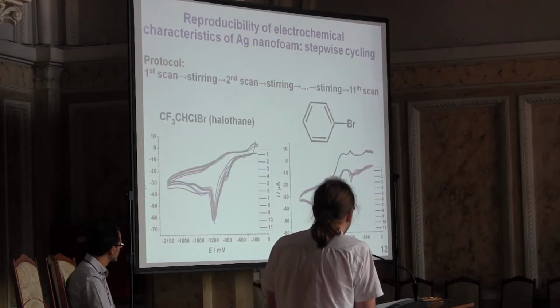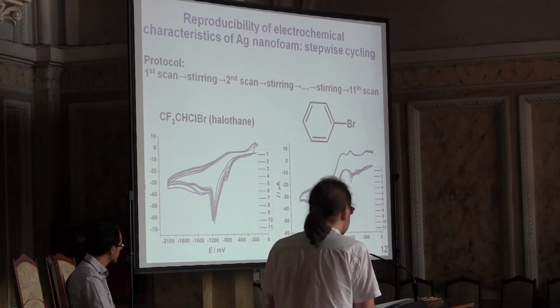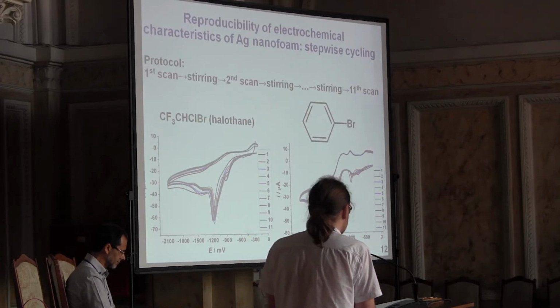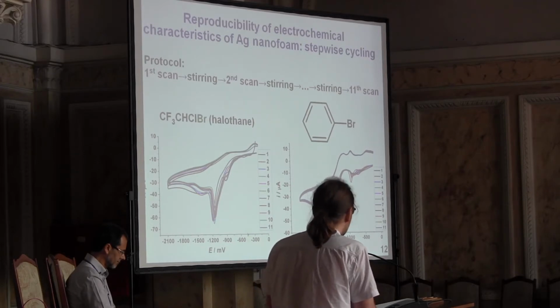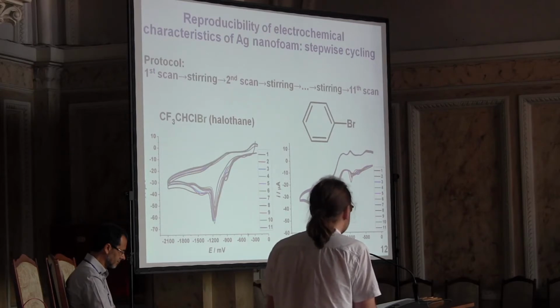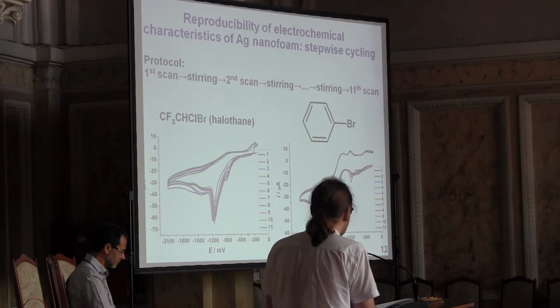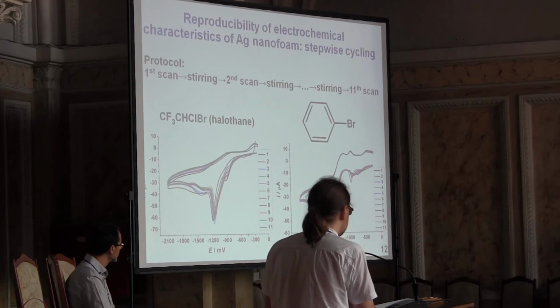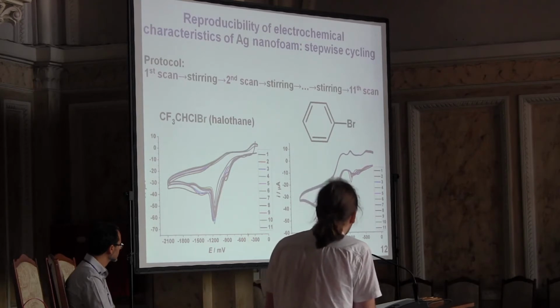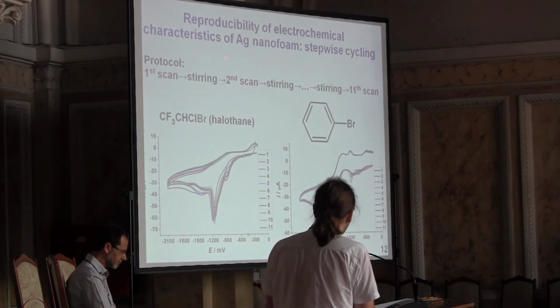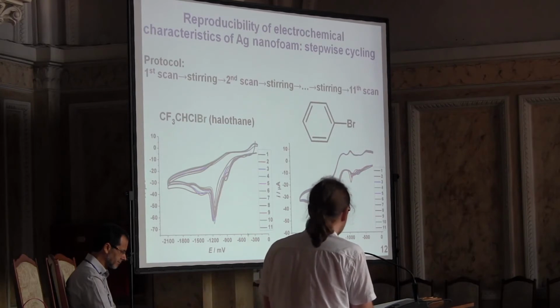In order to study the stability of the silver nanofoam coating in time during the reaction of organic halides reduction, we subjected the nanofoam to continuous cycling and found that electrocatalytic performance didn't degrade with cycling. However, it's true only if we stir the solution, thoroughly stir the solution between each two scans.